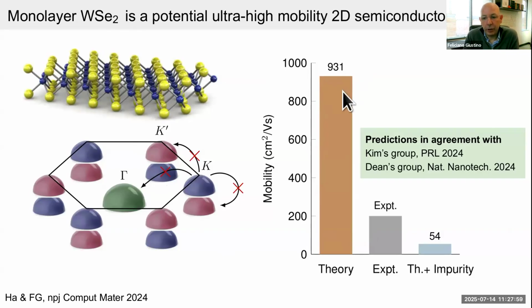And it's actually a little bit at odds with what was reported in the literature, where people could not reach anything above 200 centimeters squared per volt second. So there was a bit of a discrepancy. When we published this result, we got a little bit of pushback, essentially telling us that maybe our calculations were just inaccurate and not able to predict experiments. However, as soon as we incorporated the effects of impurities in the sample, the mobility dropped from 1,000 to about 50, and this is much more in line with what has been observed.